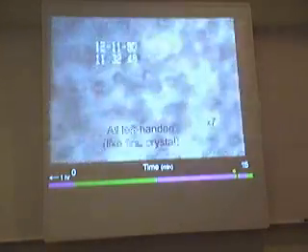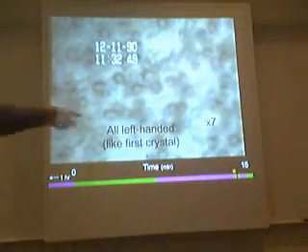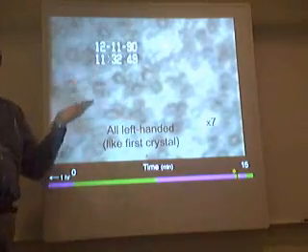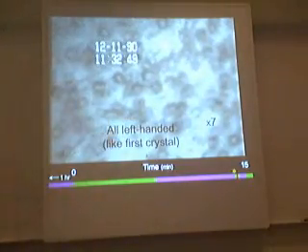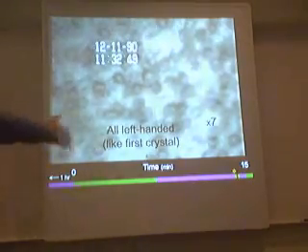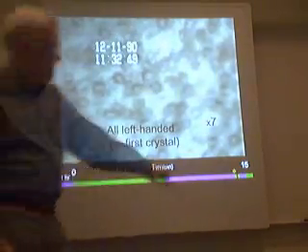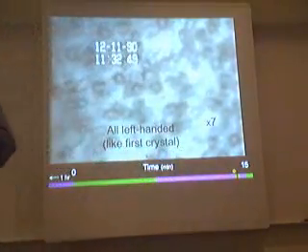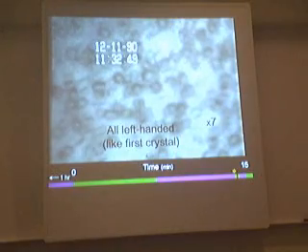And if then we look at it for another, whatever, minute, and blow it up times 7, you see there are crystals full, and they're all the same left hand as the original crystal. So I think there's no chance, you've been stirring for an hour and 15 minutes, that everything happened within 15 seconds, to me, means that the collision is what started all these crystals growing. So secondary nucleation.